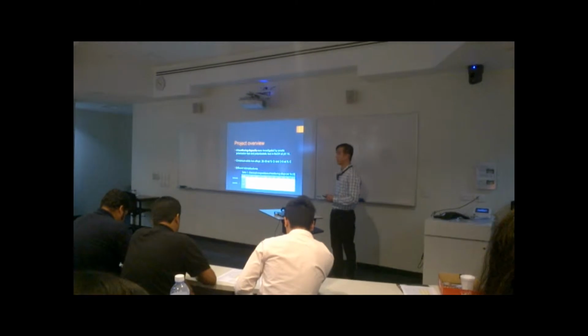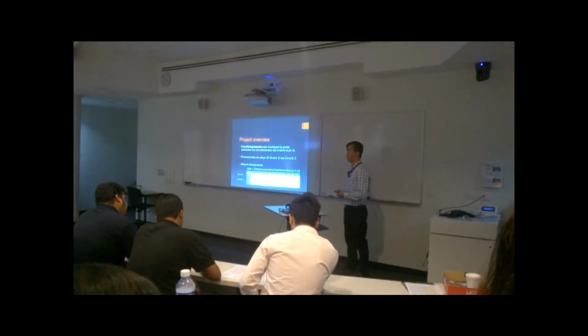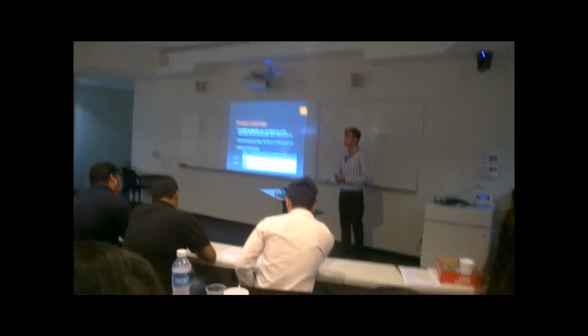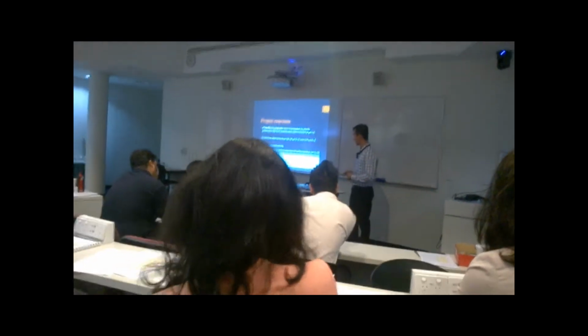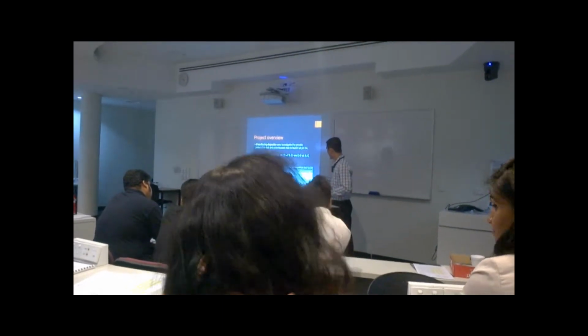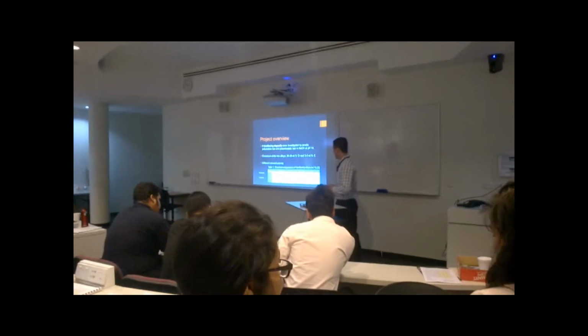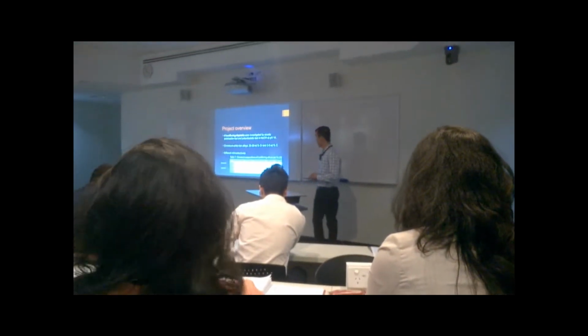The solution I use is sodium hydroxide with high pH. I try to simulate the solution used in the aluminum processing industry. All the alloys I use were chromium white iron alloys. The significant feature about these alloys is that they have a very high carbon and chromium content. So you can have a look at the carbon and chromium content of the 4 alloys here. The carbon content ranges from 3 to 5%, while the chromium content ranges from 20 to 30%.